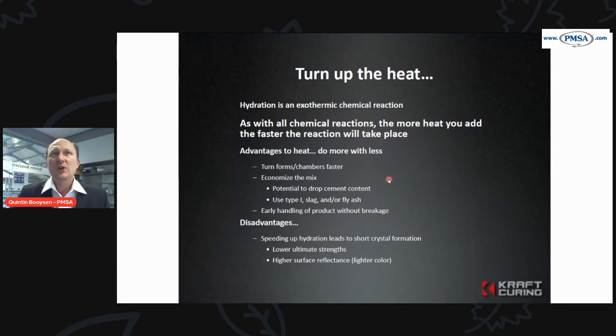So a good curing system will economize that heat by trapping it and keeping it inside your system, inside your curing chamber, underneath the plastic, underneath the sheeting, whatever you're using. It's critical to use that free heat that you've already paid for in every bag of cement. It's not there when you buy it. It's not that the bag is hot. It's when the water gets added to cement, the exothermic reaction releases heat, and we try and capture that heat and use it to the best advantage we can.